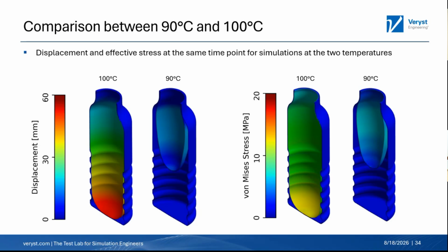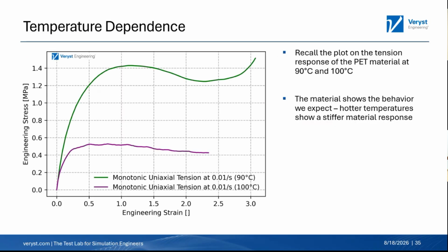You might say to me, Sean, well, what happens if we go to even higher and higher temperatures? Isn't that going to get better? Well, as Scott talked about earlier, where we have these crystallization effects, that's not always true. So I'm bringing up the monotonic data we had for 90 and 100 C, right? And you can see there that we're getting a very different response based on that temperature between there. But if you look closely, you're going to see that this is a little bit different than you would expect.